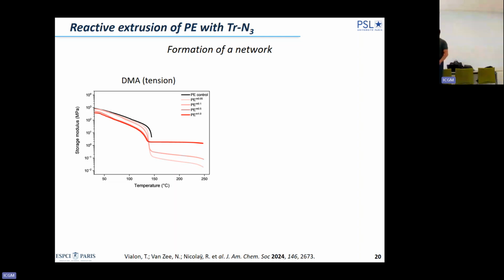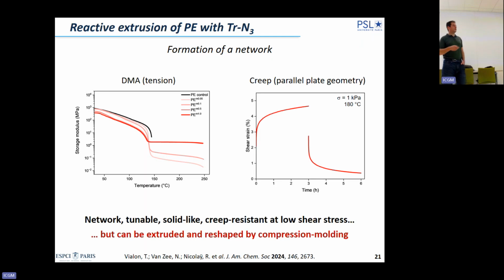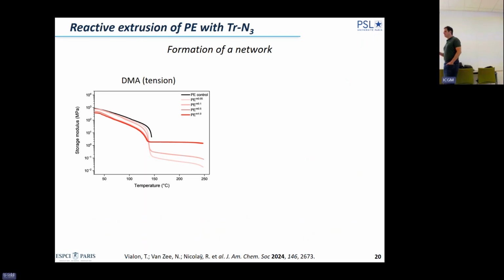This is related, we believe, to the fact that our system is inhomogeneous. One point that I did not mention yet is that our additive, by design, is not miscible with PE, and it is not miscible with PP. So I say by design because this allows us to have a very high local concentration of the additive. And in our case, we would like to make oligomers. If you want to make oligomers, you want these molecules to work together. So you want to have a very high local density.